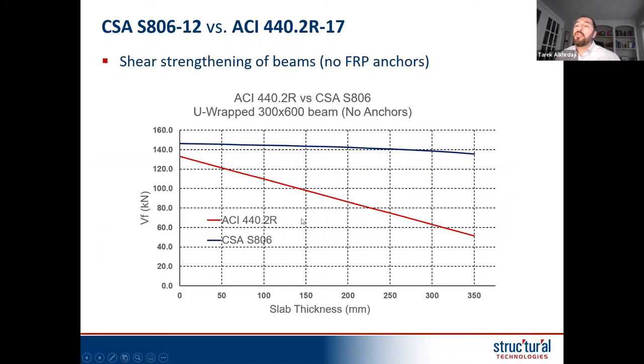And here's something I wanted to show you, why I thought that is critical. The ACI, for example, the American standards, account for the thickness of the slab, while currently the CSA does not clearly say that. If you miss that and you take, let's say, a simple beam with a different thickness of the slab, you can see that as you increase the thickness of the slab, you reduce the depth of your effective FRP reinforcement, so the capacity will drop.